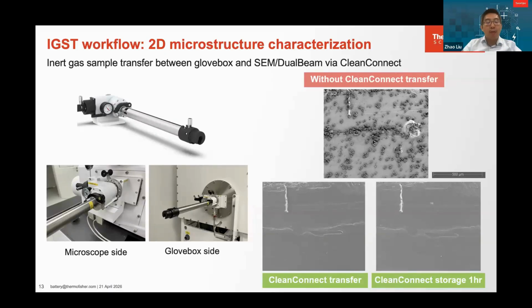Inside the capsule, the sample sits in a positive argon environment that mimics the situation of the sample actually sitting inside a glove box. This way the sample is well protected compared to the vacuum transfer, because you have limited risk of leaking issues when you transfer the samples. On the right is a comparison of a sample using lithium metal during the transfer with or without Clean Connect to protect the sample. The result is obvious: if you don't have the sample transfer protected by the argon environment, your sample is severely damaged.